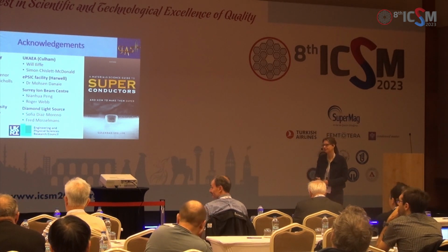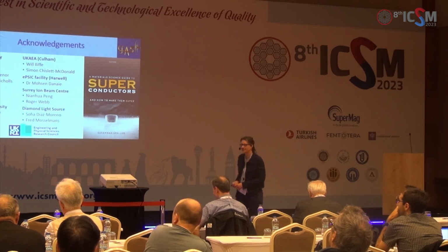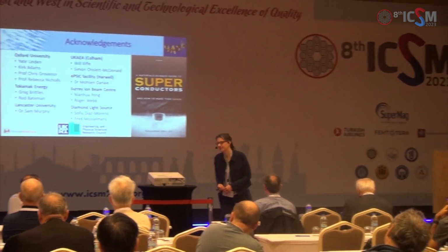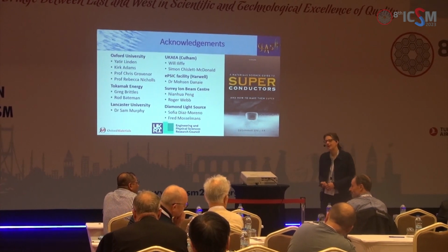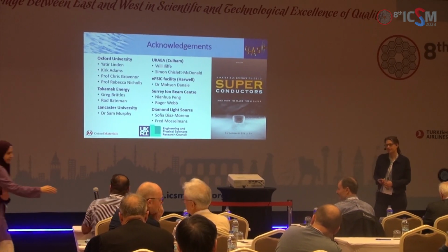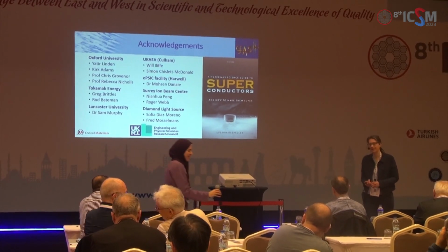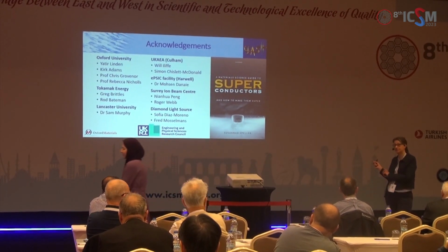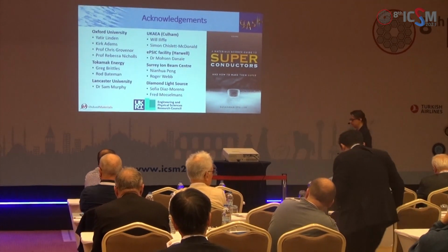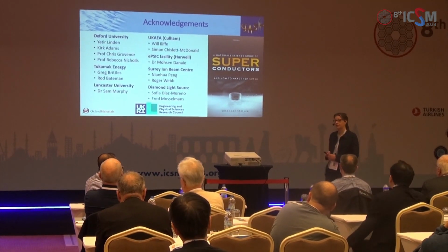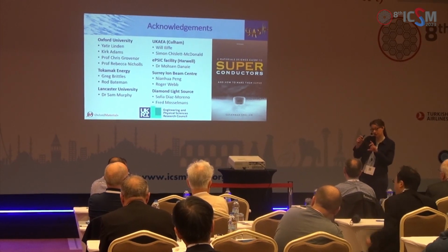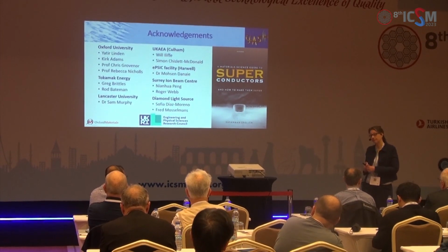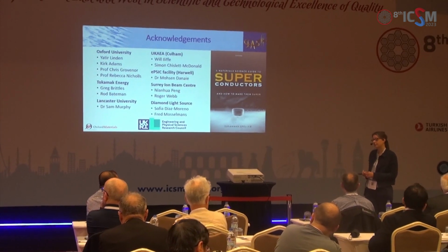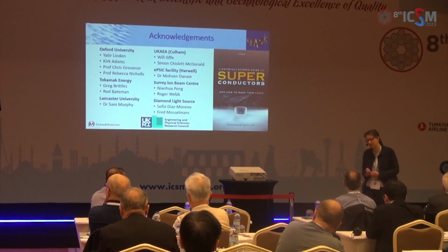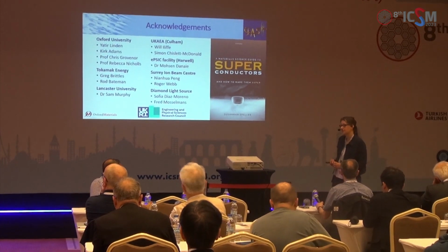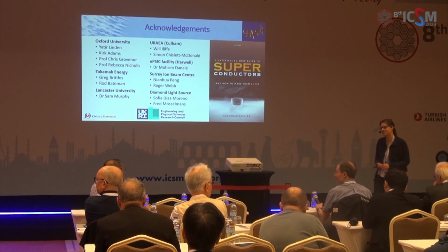Thank you. Quick question. Have you also done energy loss spectroscopy for the oxygen in some of these materials? Yeah, so in the TEM you can do energy loss spectroscopy, which is exactly the same as the absorption spectroscopy in terms of the physics. We've done a little bit, but the nice thing about that is that you can get spatially resolved information. We've tried a little bit, and I know that other people have been successful. In our microscope, when we did it, we couldn't get enough signal. So this is on our to-do list for the next couple of years.